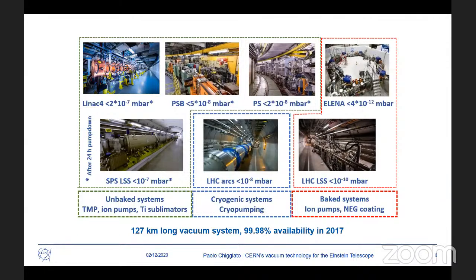In the other part of the LHC, where we need a much higher vacuum, sorry, lower pressure, we have two strategies for pumping. The one for the room temperature areas, where we massively pump with non-evaporable getter thin films. We have a 6 kilometer coated with 1 micrometer of this film, titanium, zirconium, and vanadium. While in the cryogenic parts, of course, we profit from a fantastic cryogenic system, which give us surfaces at 1.9 Kelvin, which is the temperature of the cold mass of the magnets.